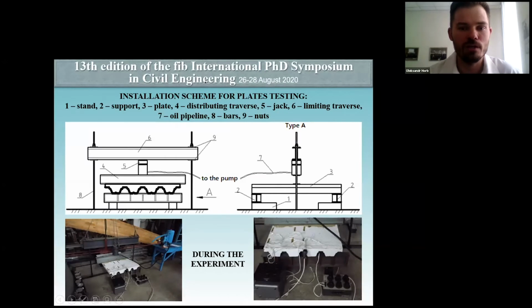The most important to us was to check work of profiled flooring slab, because we don't use any additional reinforcement in this way. We want to see on each stage, every stage of working steel and concrete without any reinforcement. In this slab, we have only profiled flooring, steel profiled flooring, and concrete block. And in time of producing, we put layer of glue equal 3 millimeters on profiled flooring, and then in 30 minutes we add liquid concrete to this slab, and after hardening of 28 days we try